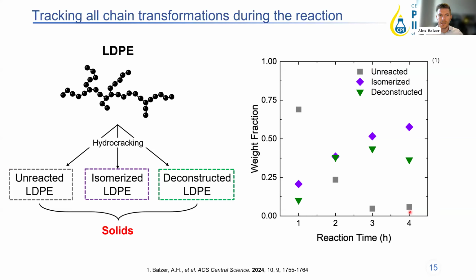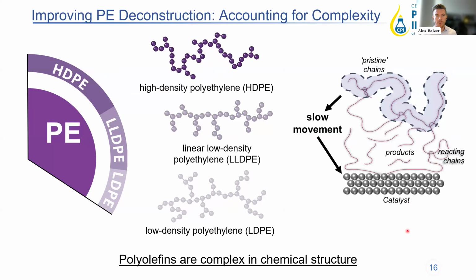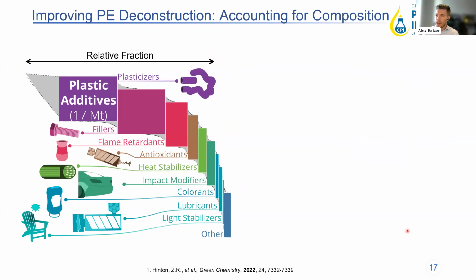And so this really comes back to understanding the kinetics and the diffusion of these polymers and how that really affects your reaction progress. So now we have this way to track the very, very small architectural changes. So we can keep zooming out and understanding more and more about the plastics during their hydrocracking. So like I said, since we have a way to track the changes, we're starting to investigate how the different branching architectures affect your product yields, how their molecular weight distributions affect your yields, because now we've unlocked this pathway to understand it better. But we also can zoom out towards the composition of the plastics that I was talking about.